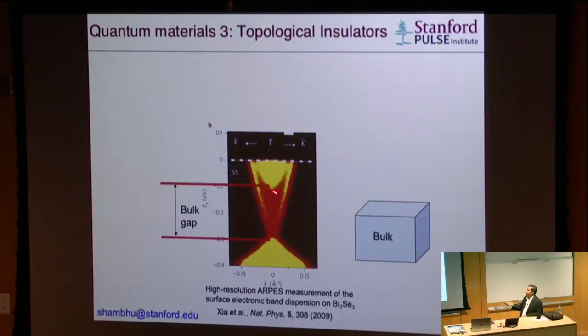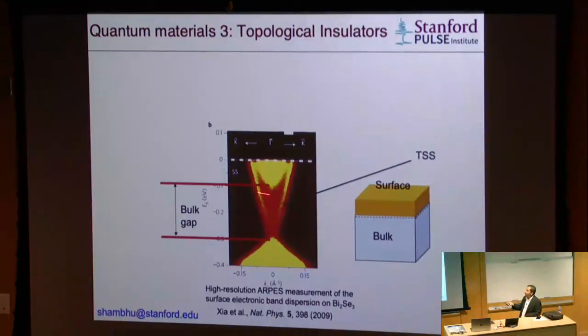There is a band gap. The bulk of the crystal has a band gap. This is the valence band. This is the conduction band, and the gap is almost exactly 0.3 eV. So the bulk is an insulator because it has a band gap. It doesn't need to be an insulator; it could be metal, depending on the Fermi energy, but it has a band gap. Now you see these are the surface bands, and the surface bands actually close. There is no band gap. The surface of the material is fully conductive, like a metal. On top of that, these bands are protected by what's called time reversal symmetry protection. So you have to flip the spin to go from this side to this side. So that's my 1 minute introduction of three-dimensional topological insulators.